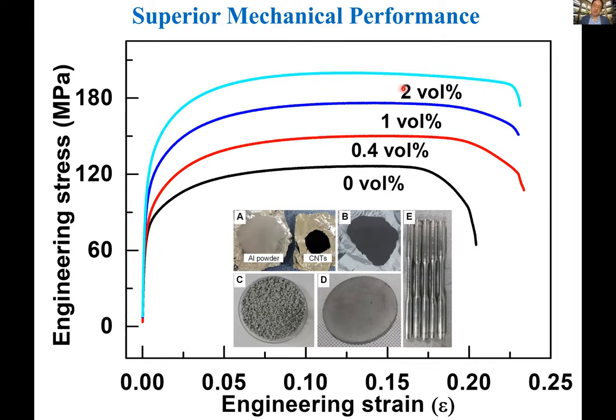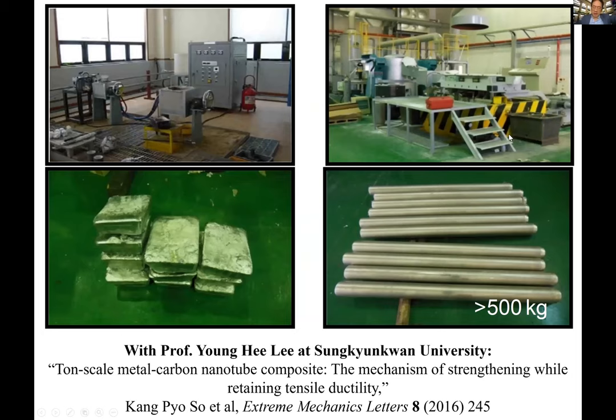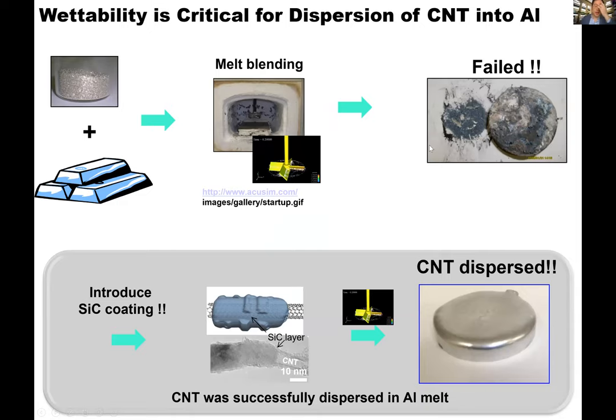2 volume percent is about 1 weight percent carbon nanotube. And with the current price for a multi-wall carbon nanotube, this would only kind of double the cost of your aluminum. So this is economically okay. But it gives you up to 50% improvement in tensile yield stress without sacrificing the ultimate ductility. And this has been scaled up, so you can make a lot of it. And the trick is wetting.